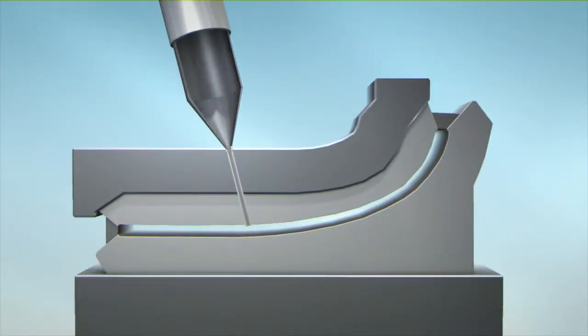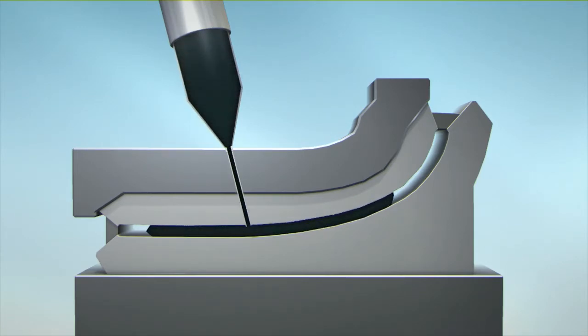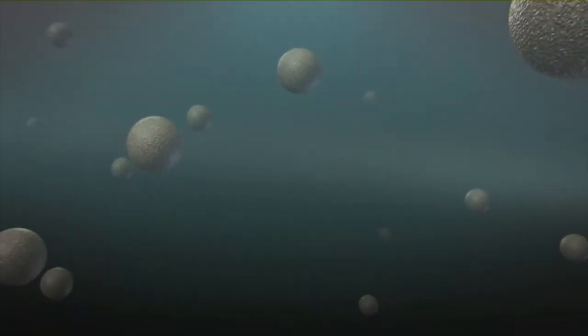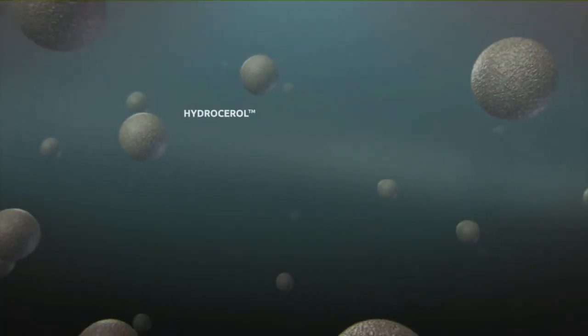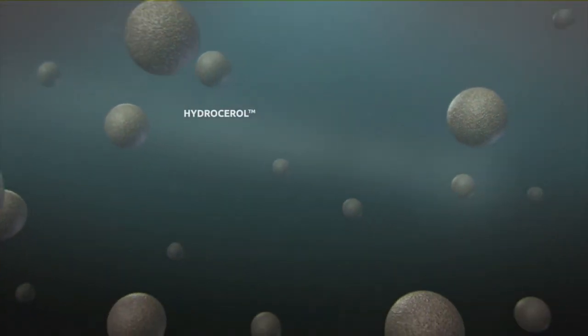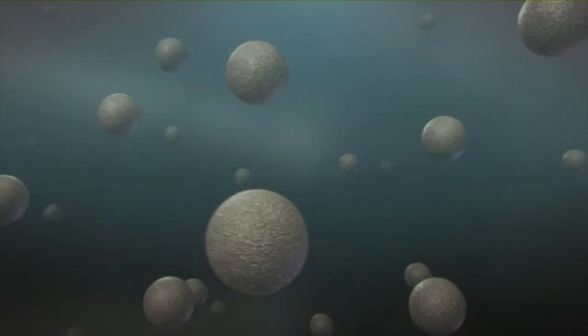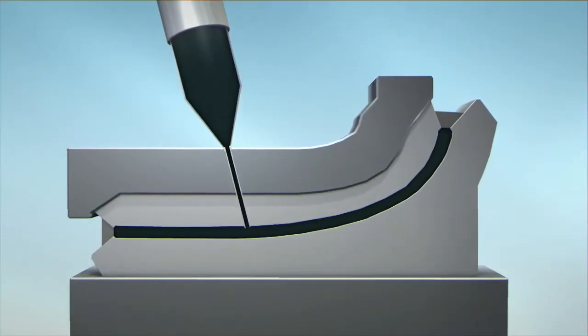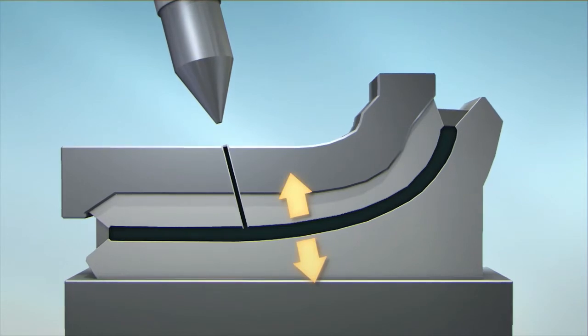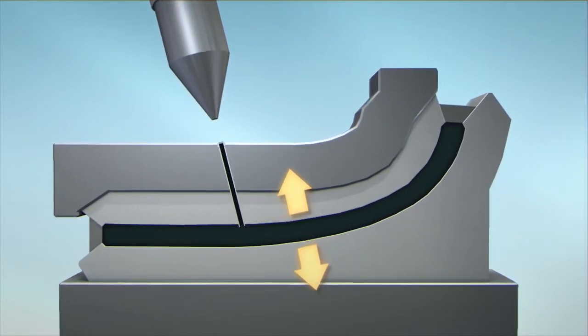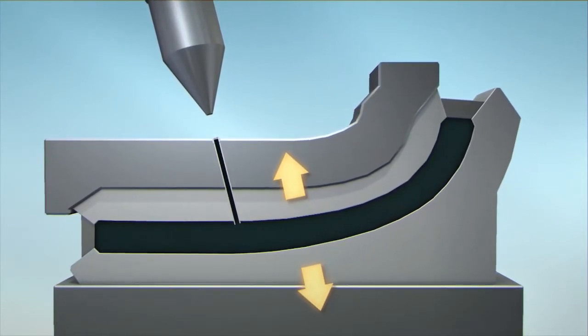To manufacture these moldings, plastic melt is pressed into a hollow injection mold. A precisely dosed amount of HYDROCEROL embedded in plastic granules, known as master batches, is added to this plastic melt. The hollow mold is opened slowly after filling to allow the foaming agent to exert its effect from the inside